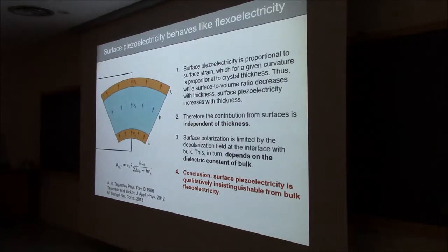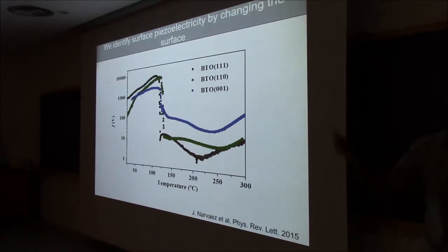This is true, but I have a small disagreement in that you can actually change the surface. You can change the surface, for example, by changing the orientation or by changing the termination. In the case of BTO, it's very clear. If we measure BTO with 3 different orientations, we see very different total flexoelectric effects when we shouldn't expect such a large difference for a cubic system. So we think that this difference in the intrinsic regime is due to the different type of surface that we have due to the different orientation of the crystal. Is that clear?